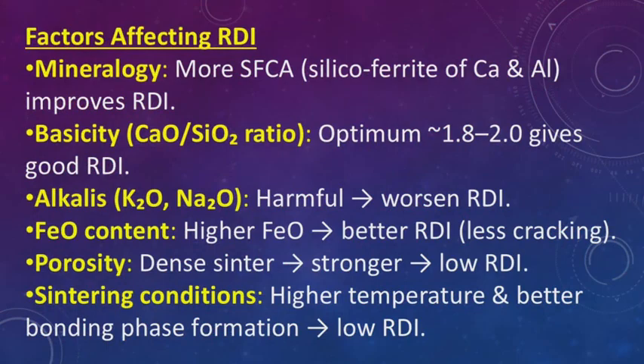Factors affecting RDI. Mineralogy. More SFCA, silicoferrite of calcium, improves RDI. Basicity, CaO by SiO2 ratio. Optimum 1.8 to 2.0 gives good RDI. Alkalis, K2O, Na2O. Harmful, worsen RDI. FeO content. Higher FeO, better RDI, less cracking. Porosity. Dense sinter. Stronger. Low RDI. Sintering conditions. Higher temperature and better bonding phase formation.